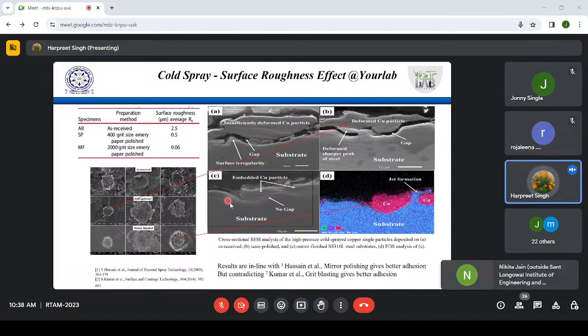For example, this is a very good study done by my student Surinder Singh on the surface roughness effect. Here we had this combination of SS316L steel and copper, right? This is a very new application which we explored for nuclear reactors. They wanted to develop very thick coatings of 3 mm on the stainless steel. This is very challenging because they wanted pure copper coatings without any oxidation. This work is being done in several countries because they want very nice oxide-free coatings of copper. Not for corrosion or other things, but for passivation of plasma currents and so on. For this, they need very high thermal as well as electrical conductivity.